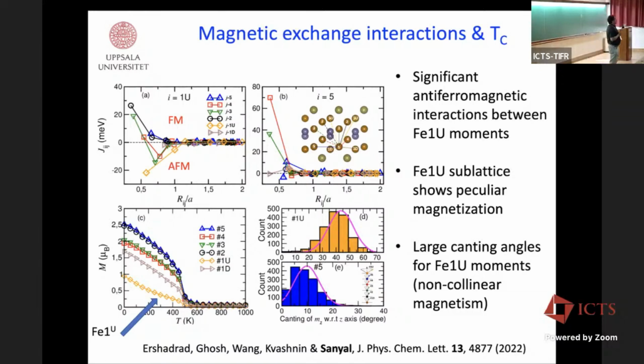Okay. Now, when you take all these interaction parameters and do Monte Carlo simulations, you can plot the sublattice magnetization as a function of temperature. And then you see that different sublattices, for example iron 4 and iron 2, are degenerate here, and these two are degenerate. But a little bit of unusual behavior is seen for the iron 1 up sublattice, which doesn't look like a real ferromagnetic interaction. So when we saw that, we were interested to see what the magnetic structure is for that sublattice at a very low temperature.